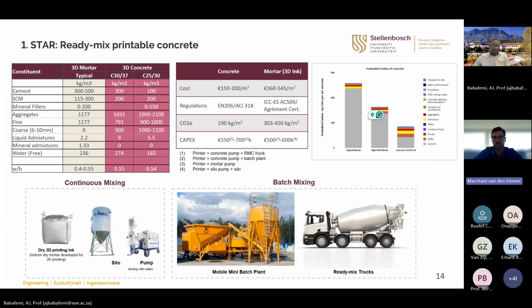So John, if you could please move to the next slide there. In the industry, we have three main methods of supplying printable concrete. For continuous mixing applications, it's typically a mortar, so material with a pretty fine aggregate. As John pointed out, this tends to have a pretty high binder content, binder referencing the cementitious content in this material, which can be split between the cement itself and the supplementary cementitious materials that are used to replace it, and mineral fillers that can be used, which all build up the powder fraction. But as you see for mortars, we're looking at the range of about 800 to 1,000 kilograms per cubic metre, no coarse aggregates, and then an admixture package used to facilitate the workability properties that we require.